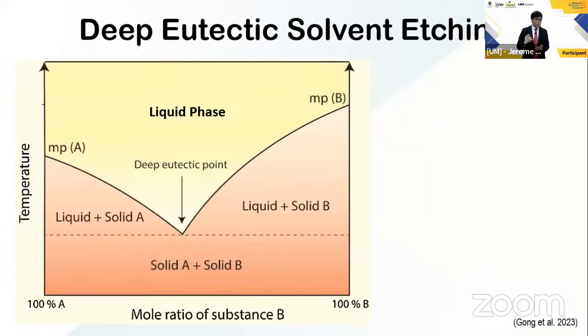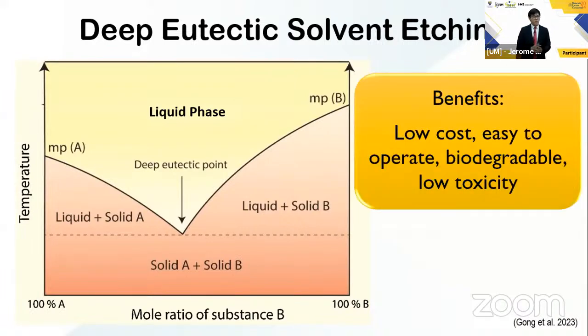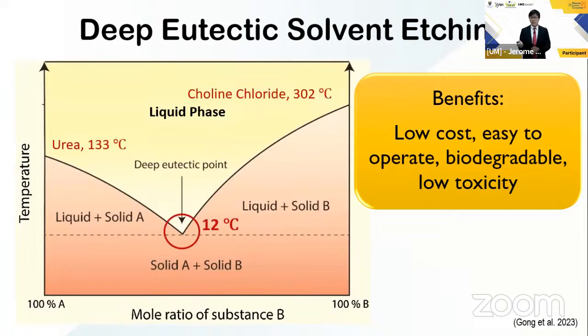Deep eutectic solvent, or DES in short, is a mixture of organic solvents with a melting point lower than any individual element. They boast the benefit of being cheap, feasible at room temperature, biodegradable, and low toxicity. And the first pair of DES ever used to make MXene was urea and choline chloride, and they reached a melting point of as low as 12 degrees.